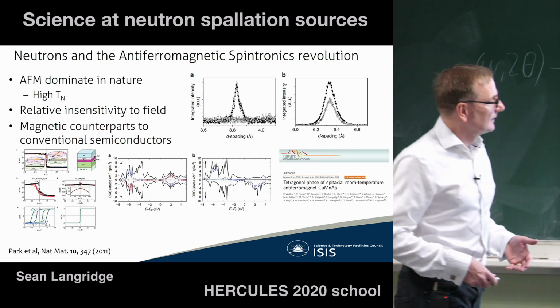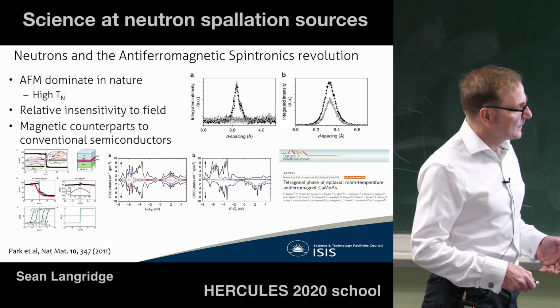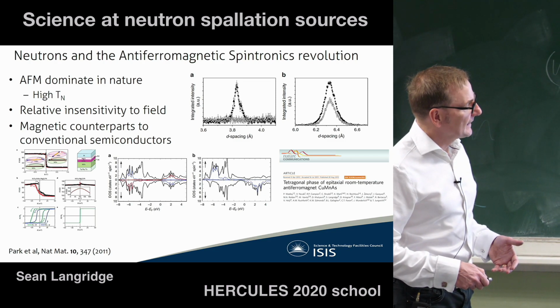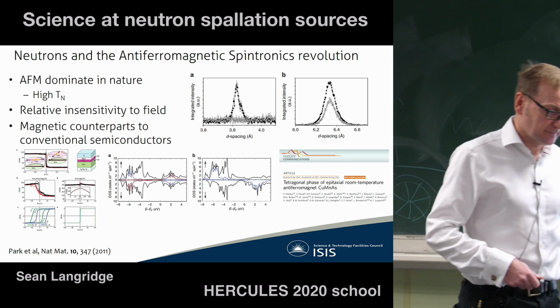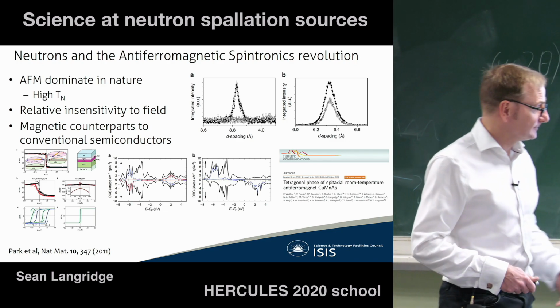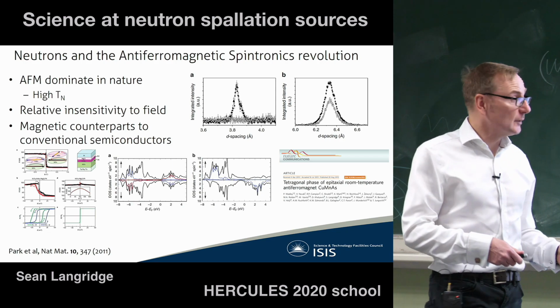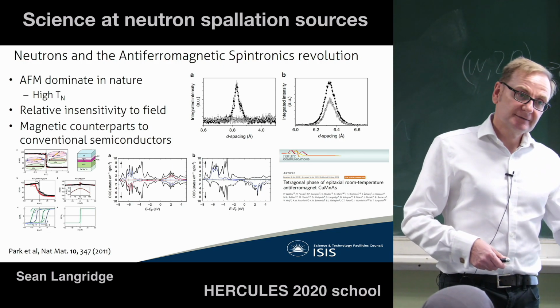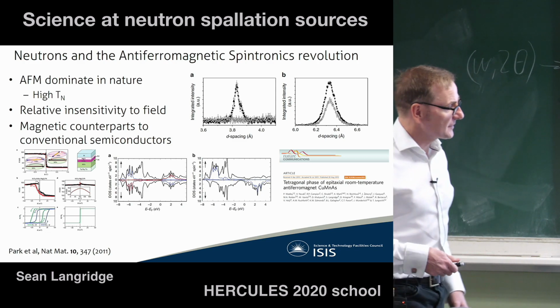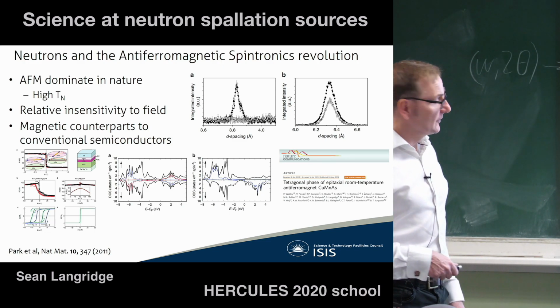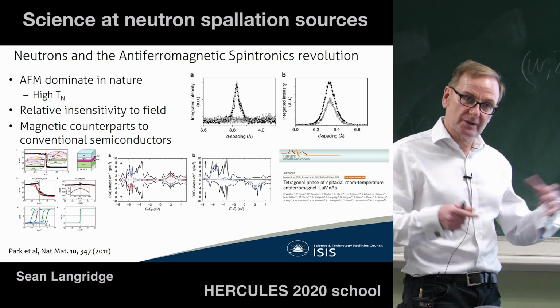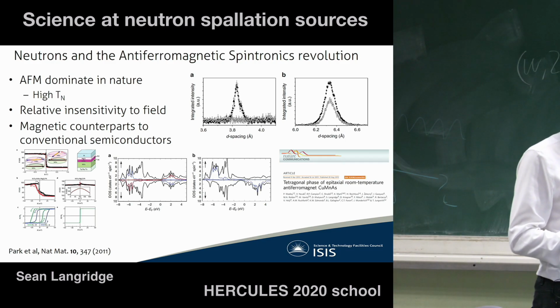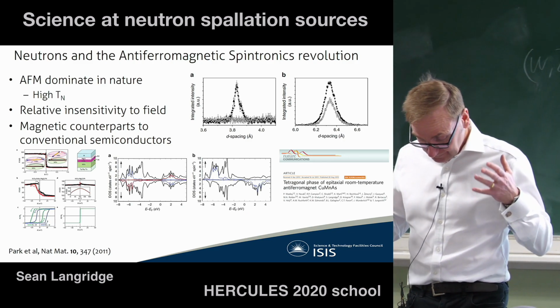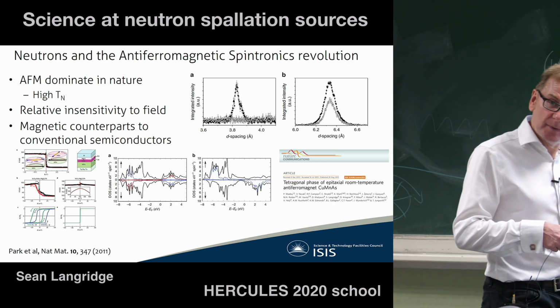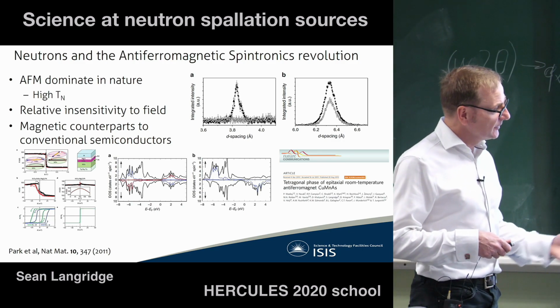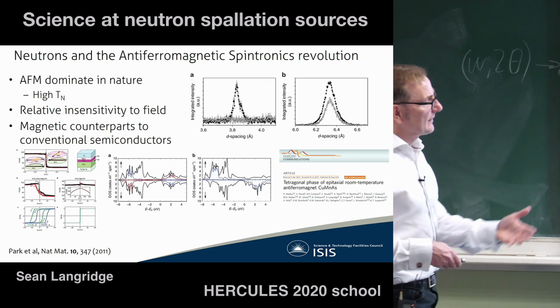As a way of showing that, this is some of our work from a little while ago, where we wanted to look at a thin film antiferromagnetic semiconductor that you can only stabilize in thin film form. So rather than a bulk crystal of however big your bulk single crystal is, this is a single crystal, but it's only a few tens of nanometers thick, sitting on a massive substrate. All the diffraction comes from the substrate, but if you look carefully, you can find the scattering from your film, which is tiny compared to the scattering from the substrate. But it's separate in Q, so that helps you, and it also shows you the flux and background that you get on this instrument.